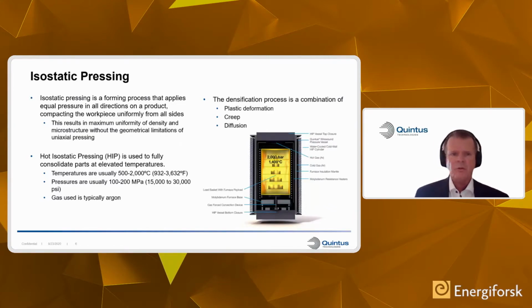I think most, if not all of you, are familiar with the principle behind hot isostatic pressing. It's basically a uniform pressure that will apply equal pressure in all directions on a product and compact it uniformly. Today, hot isostatic presses exist for temperatures up to and even beyond 2000 degrees C. Typical pressures are in the range of 100 to 200 megapascal. Gas is in most cases argon, but other types of gases can be used too. And the actual densification process is a result of plastic deformation, creep, and diffusion. So with the possibility to use different temperatures and pressures, this is something that you can elaborate with.